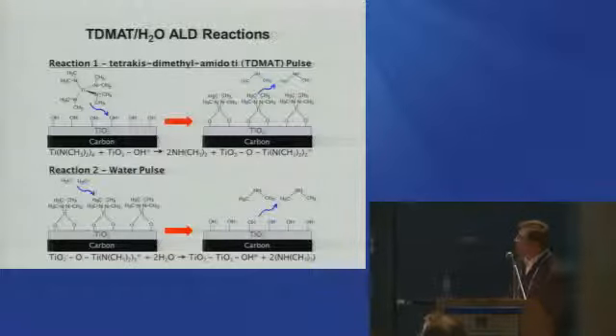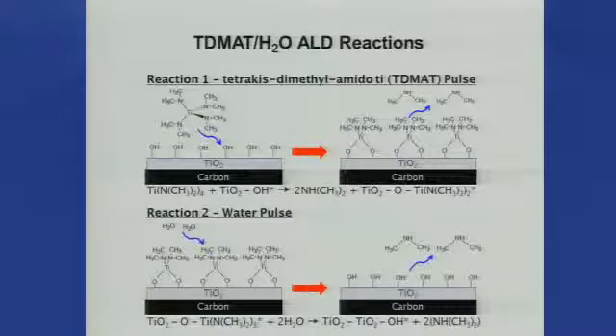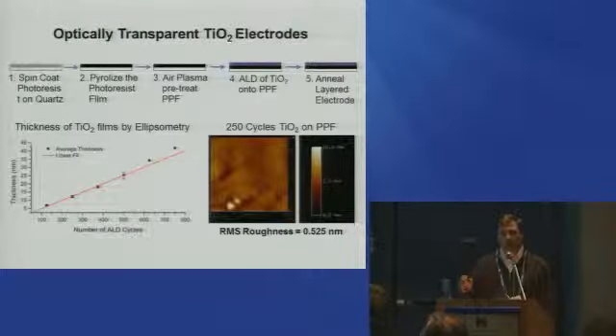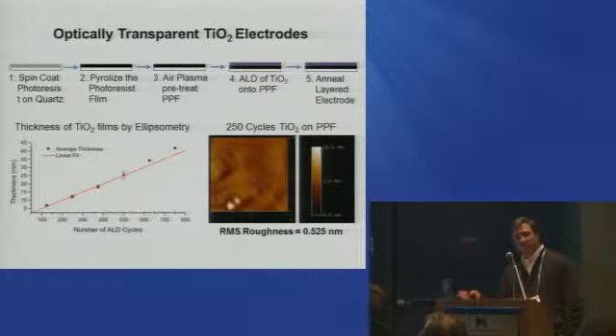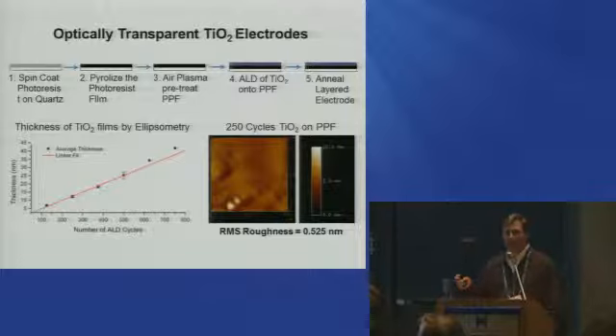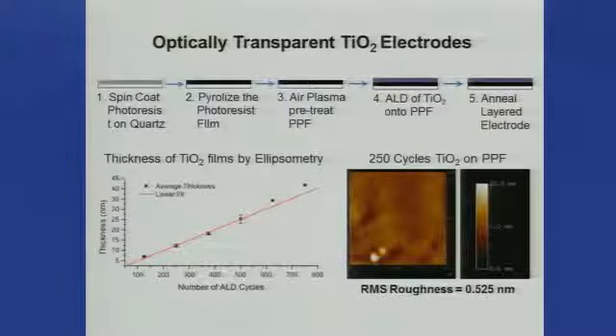In our case, we use the precursor tetrakis dimethyl amido titanium, and we pulse that in on a hydroxylated surface. We use a little bit of a plasma treatment to nucleate that first layer, and then you pulse in the water to nucleate the next phase. When you actually get into this business, what typically happens is people buy commercial instruments and they sell you recipes, right? They say, if you want to grow TiO2, this is the precursor, this is the pulse sequence, and this is how many layers. What we found, though, is that you have to be careful about understanding where the nucleation occurs in the growth. Joe showed an elegant example about how they can really control this at the molecular level and functionalize individual sites that are separated by quite some distances.